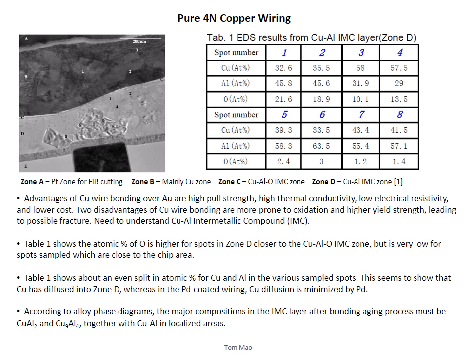The main takeaway from this is that the major compositions in the IMC layer after the bonding aging process are CuAl2 and Cu9Al4. This also shows that copper has diffused into zone D, whereas in the palladium coated wire, copper diffusion is minimized. The percentage of oxygen is higher for spots in zone D closer to the IMC zone, but the gradient drastically decreases closer to the chip area.